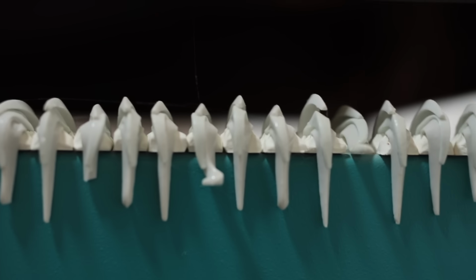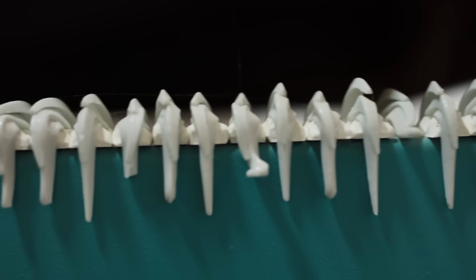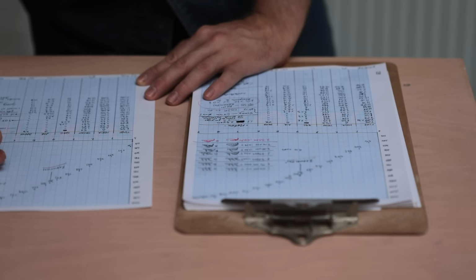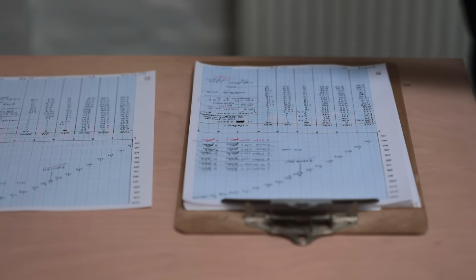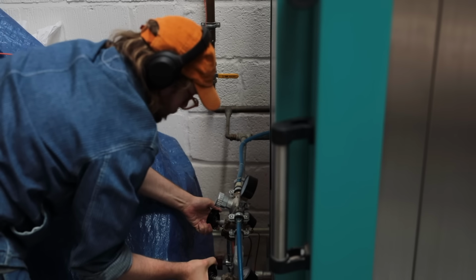This state of reduction is what causes flames to come out of the kiln, and it's these things, the pyrometric cones, which I can see through spy holes in the kiln's door, that measure something called heat work, which is heat over time, and after all three have bent over, which takes some time, at roughly 1290 degrees Celsius, the kiln can be switched off, the reduction firing finally finished.